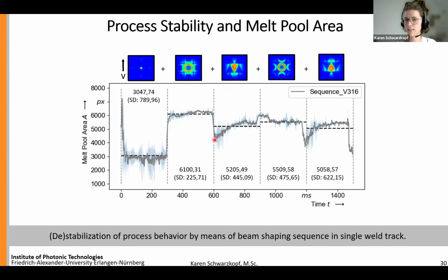And this is associated with differences in the melt pool flow behavior. For instance, the Marangoni flow can be named here, but further research, especially regarding simulation, has to be conducted to really grasp the differences here. But what we can see is that it takes a certain time, around 100 milliseconds, to really change or to really stabilize again the melt pool behavior.